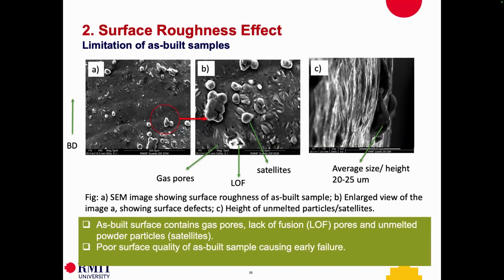So poor surface quality of as-built samples is causing early failure, but this surface quality is affected by these defects, which are lying in the proximity of the surface. And they are even making the thing worse by causing fatigue crack to initiate from the surface from one or multiple of these different types of defects.